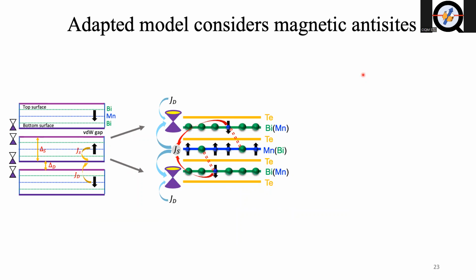It has been reported that the bismuth-manganese anti-sites living in the bismuth layer couple antiferromagnetically with those in the manganese layer. And as I mentioned before, in our case, our film is pretty much intrinsic, so we consider it pretty much well compensated, meaning that the amount of bismuth-manganese anti-site is the same as manganese-bismuth anti-site. So those defects will alter those coupling parameters as listed here.